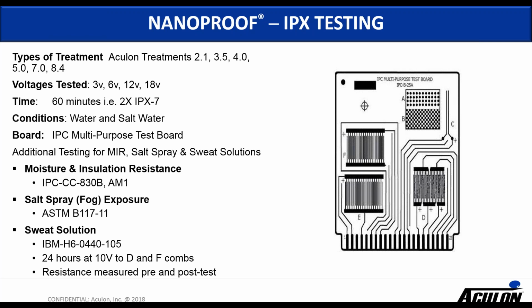So we'll get into some of the testing here that we've done to validate these IPX7 claims. What is commonly used in the industry is the IPC B25A multipurpose test board. So essentially what's done is this test board is coated at a nominal thickness with whichever coating we're testing. It's then electrically powered up and then inserted into either a salt and sweat solution or water or into an MIR chamber. And then we measure the current leakage while it's under voltage.